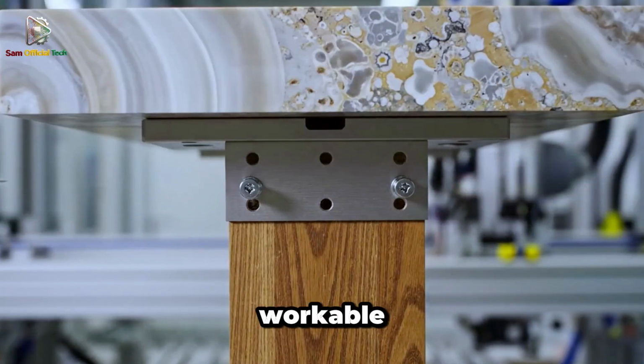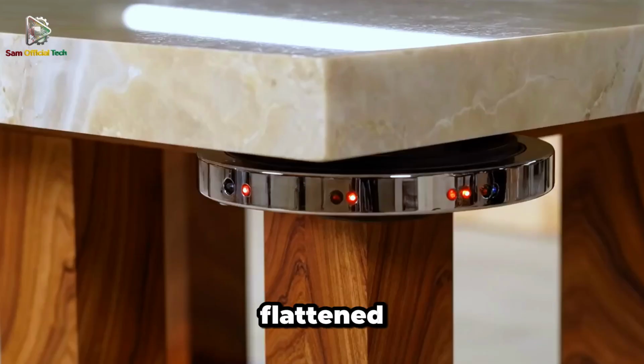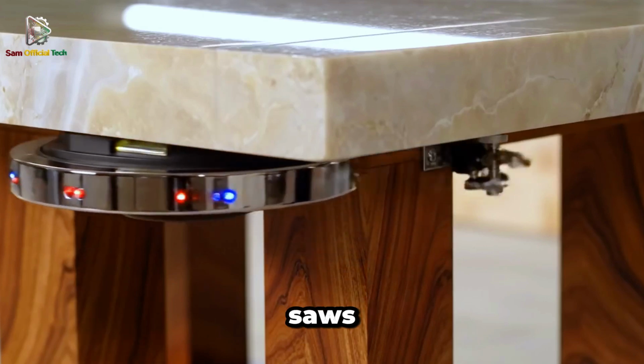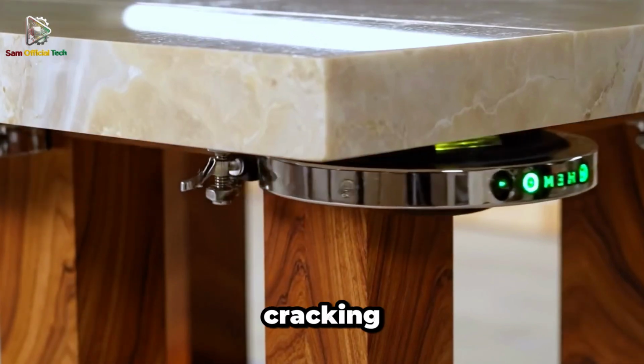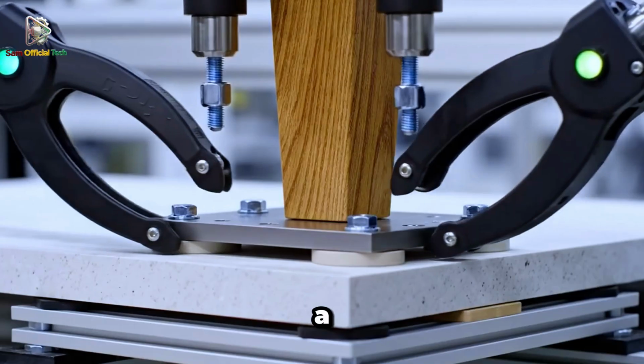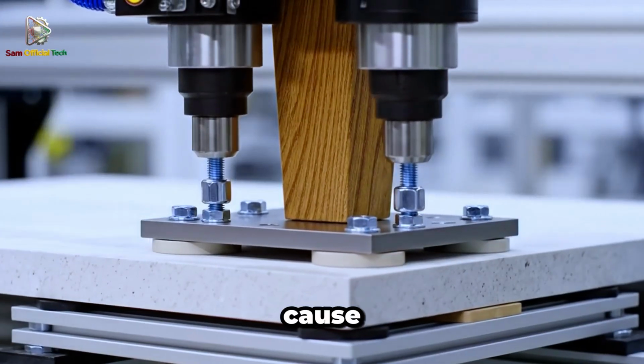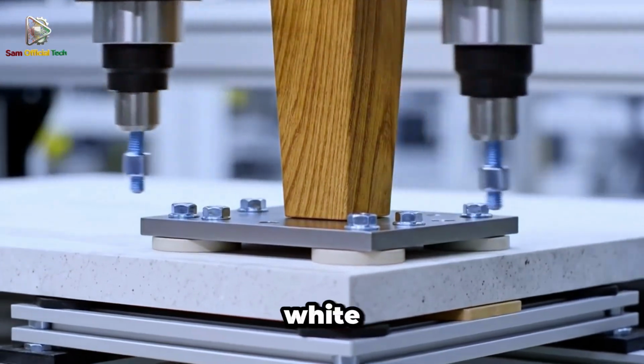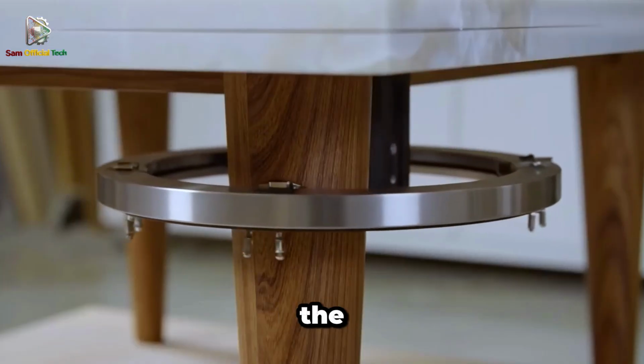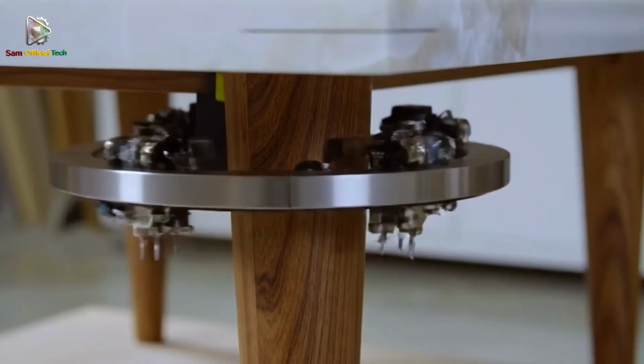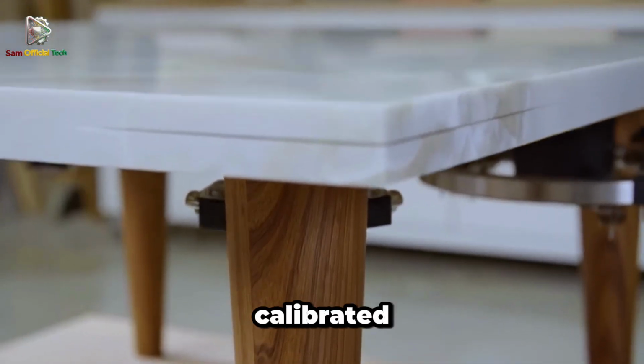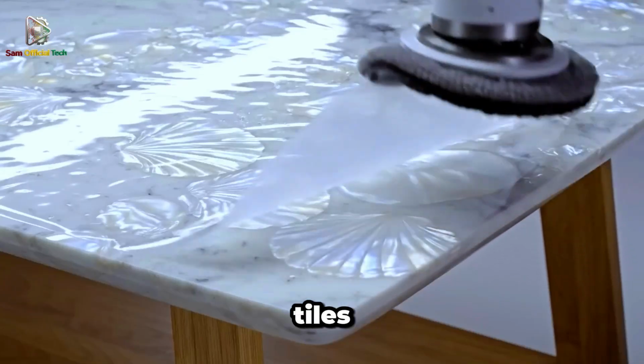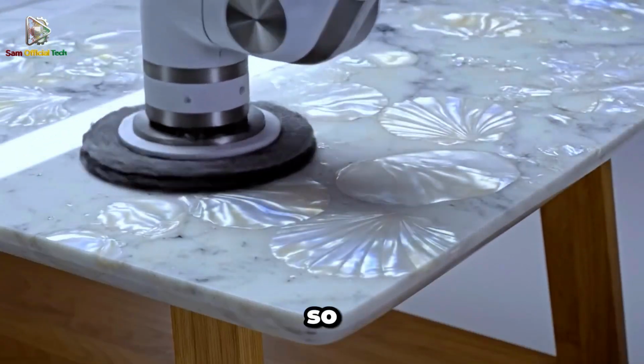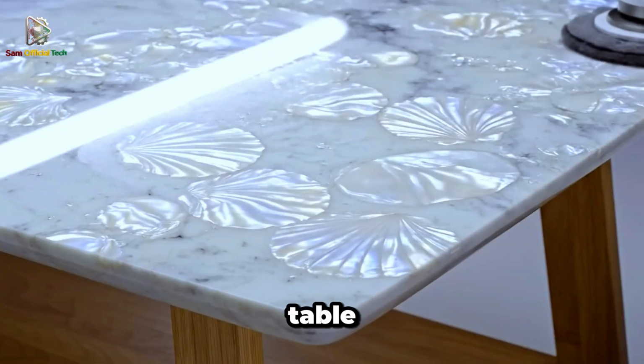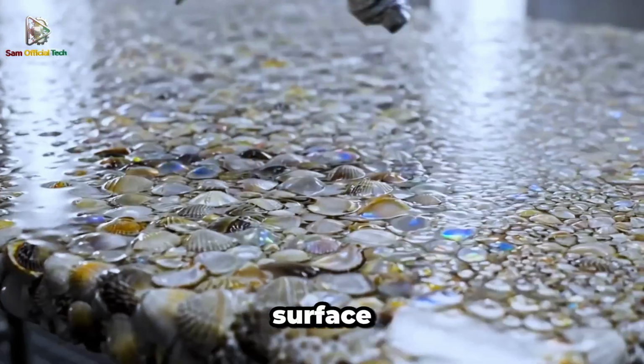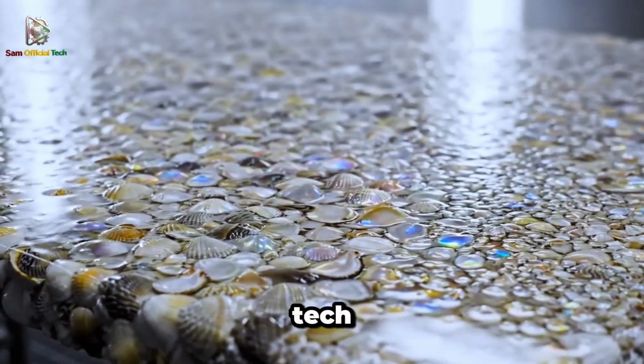For inlay-grade shell, the process becomes much more precise. Shells are cut into workable blanks, then flattened. Water-cooled saws slice sections to minimize heat and cracking, because shell is a layered composite, and heat can cause microfractures that later show as white lines under polish. The flattened pieces go through thickness sanding on wide belt sanders with calibrated pressure, producing tiles with consistent thickness, so they sit perfectly level in the table surface.